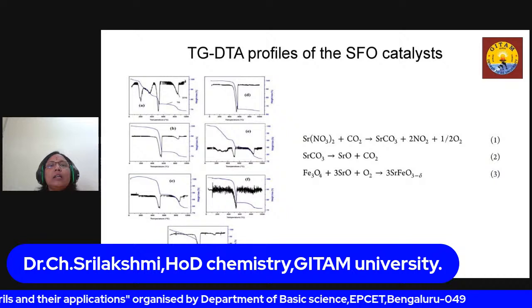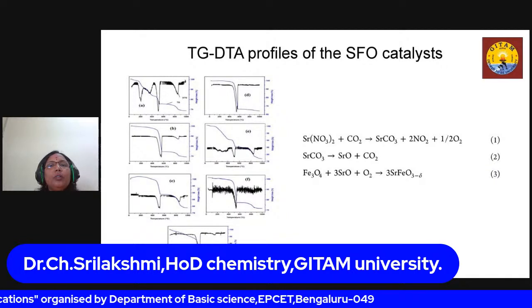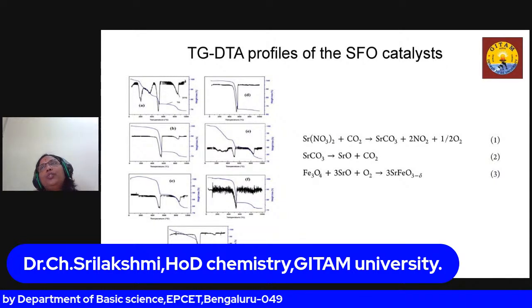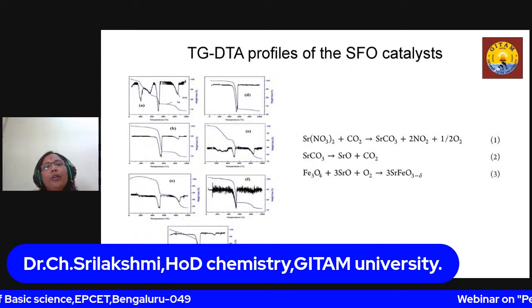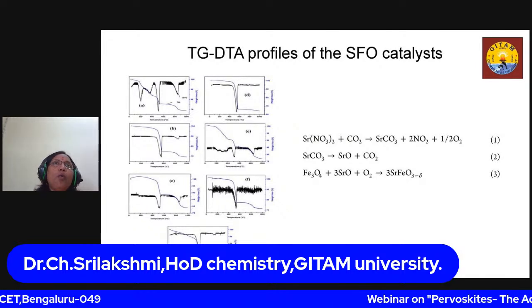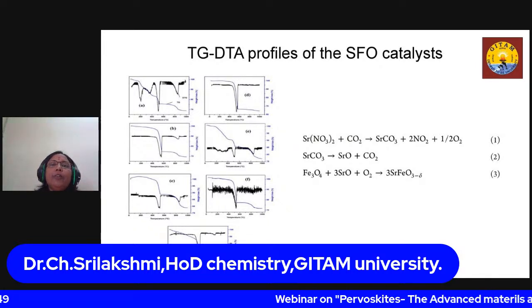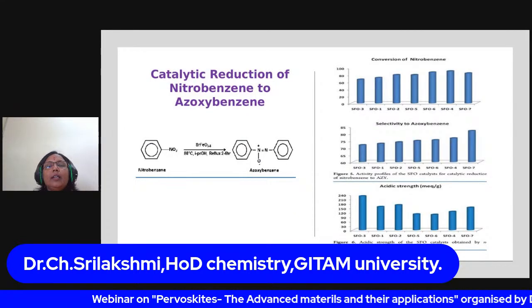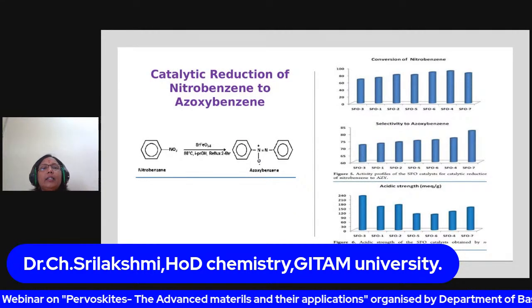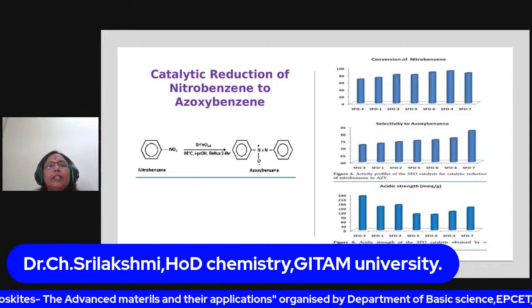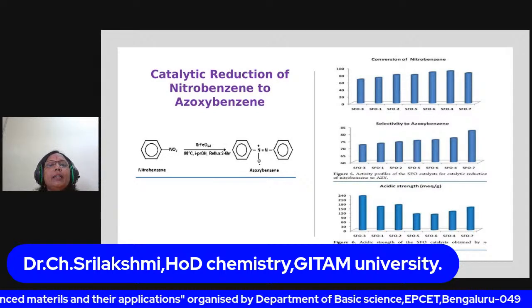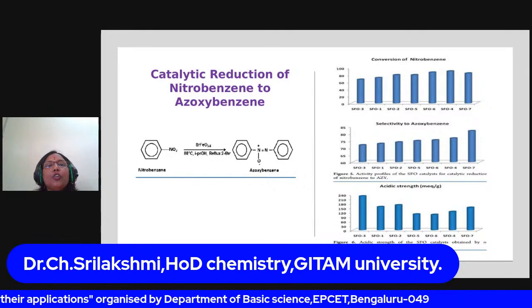So from these studies, we know at which temperature we should calcine this sample. When we calcine this sample above 850, definitely we will get this phase. That is the information we get. So once we calcined the catalyst at 850 or 900 degrees, we applied this material for the catalytic reduction of nitrobenzene.